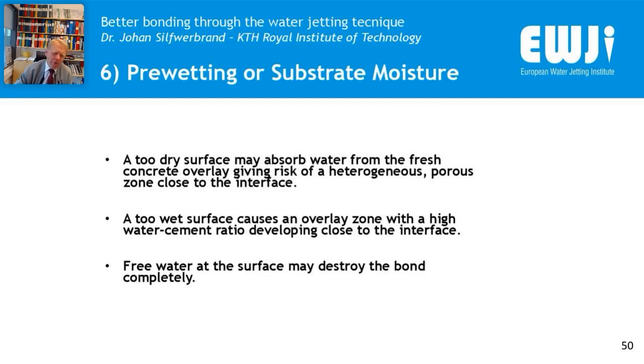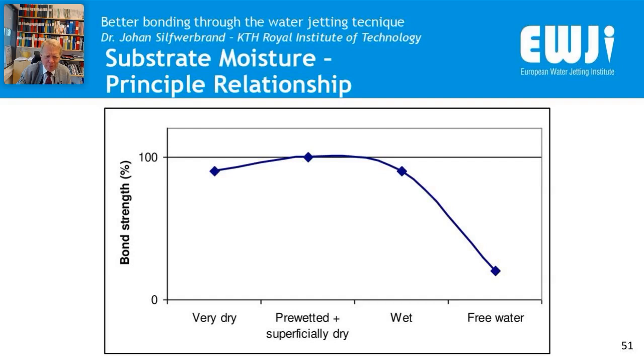It is very difficult if you have free water, and I have investigated a damage on such a site, where they cast concrete the day after a heavy rainfall, and that was a very poor bond because they had a lot of free water, and they are not using concrete for underwater repair, which you never do on land. And this is just a principal sketch of the difference between very dry, pre-wetted and wet. There are rather small differences, but if you have free water, you have a poor bond.